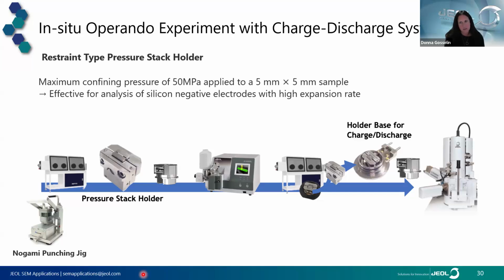It's fully compatible with our air isolation workflow. And so our charging and discharging is possible by transferring, once we created our sample, cross-sectioned in the cross-section polisher, we take it and transfer it to a base holder that has terminals in it. And those terminals will be connected to the SEM stage, which is in turn connected to a battery cycler. And by keeping the sample within the pressure stack holder, we maintain its integrity throughout the entire process.